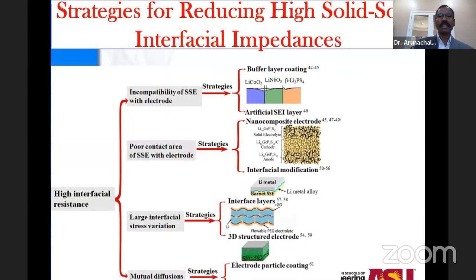But again, researchers have been able to come up with strategies. So the interfacial resistance can be handled with 4 different approaches: improving the compatibility, improving the contact area of the solid state electrolyte with the electrode, manipulating the interfacial stress variation, and also having improved mutual diffusion of the lithium ions.